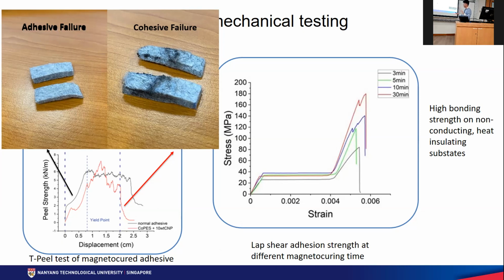Over here, in the lap shear test, we found that longer exposure to the magnetic field leads to higher lap shear adhesion strength, probably because of the higher degree of curing. But maybe when we test it at 1 hour, when the degree of cure is already very high, we don't see that difference.